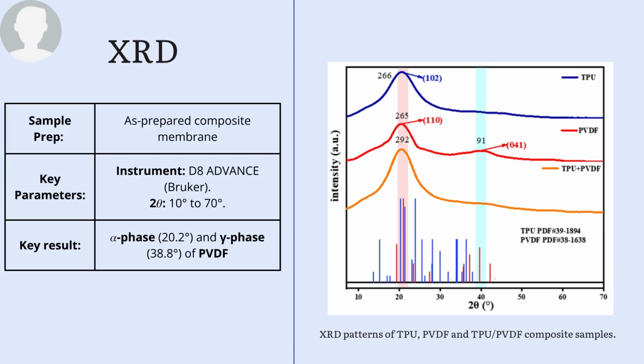The key takeaway from this data is that the incorporation of the TPU physically disrupted the orderly arrangement of the PVDF chains. This resulted in reduced crystallinity and an increased amorphous region. This structural change is critical, as a more amorphous structure translates directly to the higher flexibility and stretchability reported later in the study.